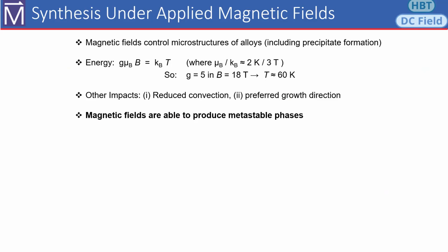Of course, growth in fields will do things like change convection, and result in preferred growth directions. And then one that I think is really pretty interesting is that magnetic fields might be able to produce metastable phases. So just think about how, I think we were hearing about in chalcogenides, and I'm going to give an example in a second, there are different structural phases that are pretty finely spaced with respect to each other in energy. So you don't need a large field to necessarily have a big impact.